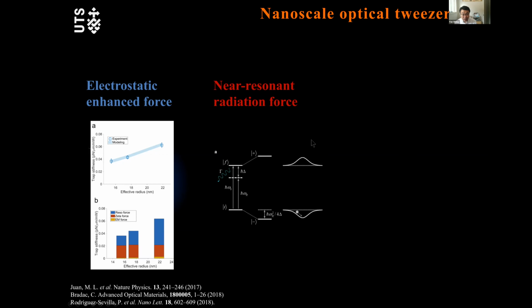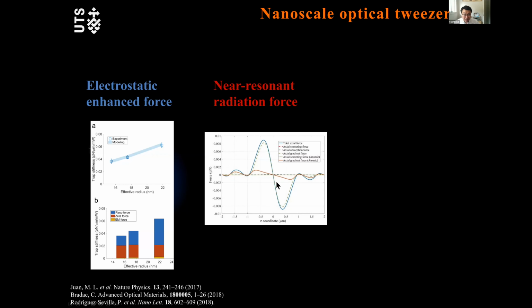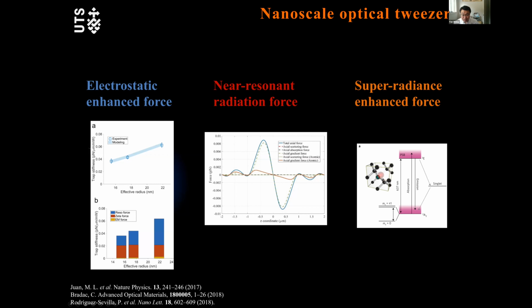Another one should be the radiation force. But with this one, I did a simulation, and it doesn't match; it doesn't give you a 30 times enhancement. It also doesn't belong to superradiance, and the literature shows that this will give about a 10 times enhancement.